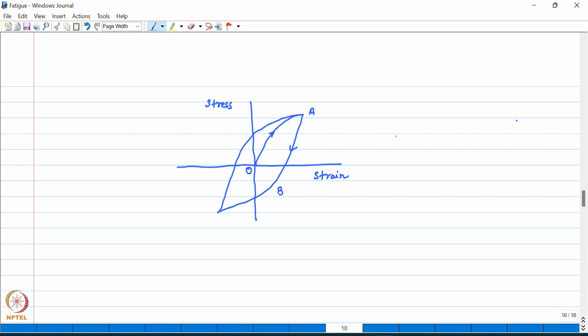So the lowering of the yield point when deformation in one direction is followed by deformation in the opposite direction is known as Bauschinger effect. Now, if it is again reloaded in tension, a hysteresis loop will develop, as you could see from here. The dimension or width of this hysteresis loop will be given by the strain range delta epsilon.